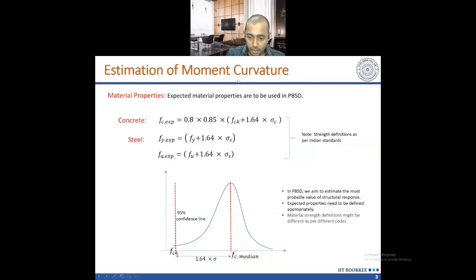And this is the median value defined, FC median. Now, along with the characteristic strength, if you add 1.64 into sigma of concrete, this 1.64 is the deviation between the median and the 95% line. This is the property of the standard probability distribution, and I am talking about the normal distribution. So this 1.64 comes from that distribution. Now this sigma c is the standard deviation based on the number of samples taken for the experimentation, a large number of samples. From that distribution, in case of concrete, it is near 5 MPa or so. So you can use this value here.